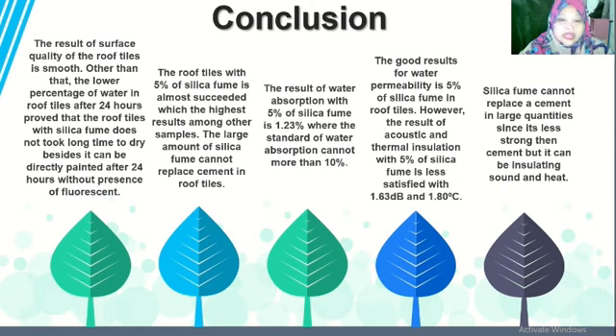However, the result of acoustic and thermal insulation with 5% of silica fume is less satisfactory, with 1.63 decibel and 1.8 degrees Celsius. As a conclusion, silica fume cannot replace cement in large quantities since it is less strong than cement, but it can insulate sound and heat.